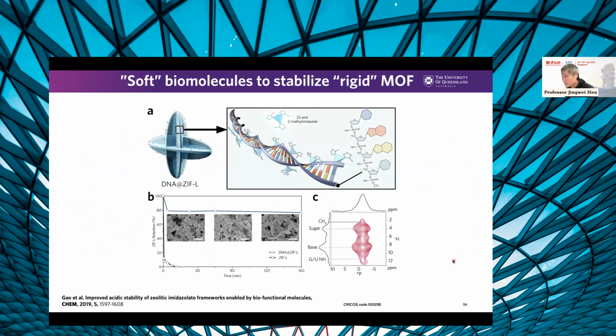How about other materials? We tried DNA, we tried polypeptide, we tried protein, we even tried living cells. They all work. In this situation, we see DNA is even better. The DNA-MOF composite can still retain around 80% of the crystallinity after nearly over 2 hours, compared with the pure MOF, which almost dissolved immediately, because they have chemical bonding at the interface. So we're not only making the bioentities much more robust, but the bioentity on the other side protects the MOF from chemical attacks.